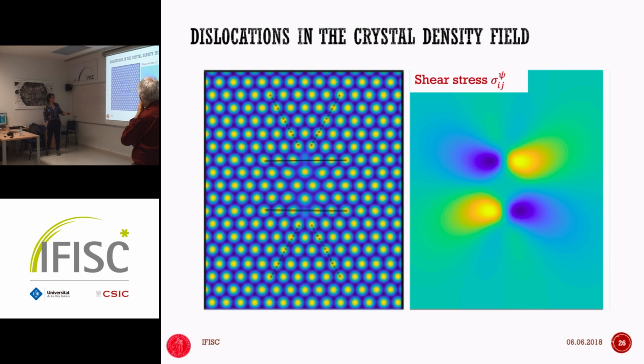If I start the simulation at very low quench, far away from the critical point, that means I have a relatively cold crystal, I will see that it's going to take a very, very long time for these guys to actually annihilate. Basically, it's not going to happen. But if I start close to the critical point, so like a warm crystal, they're going to come together. They're going to annihilate, just as if they are on the same line. Yeah. So it's different.